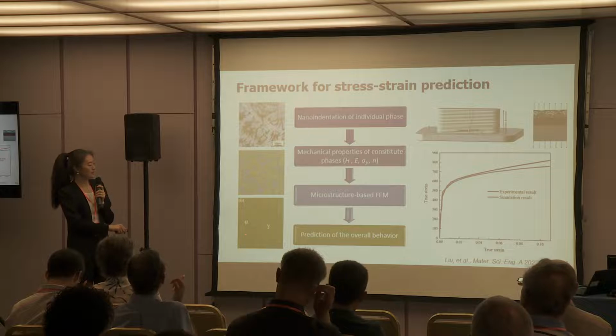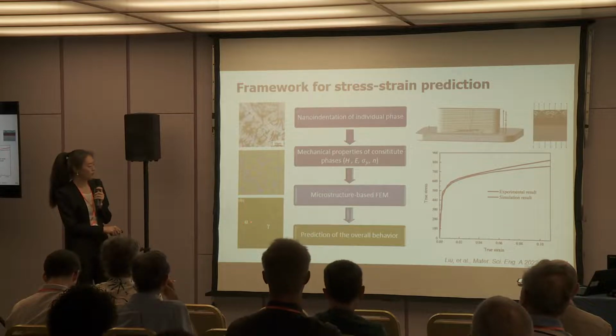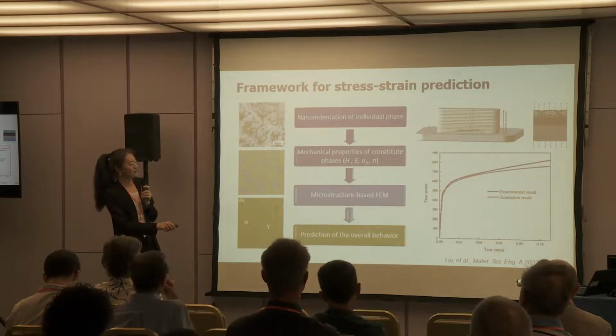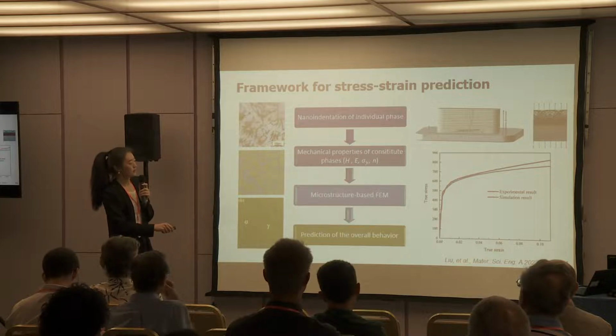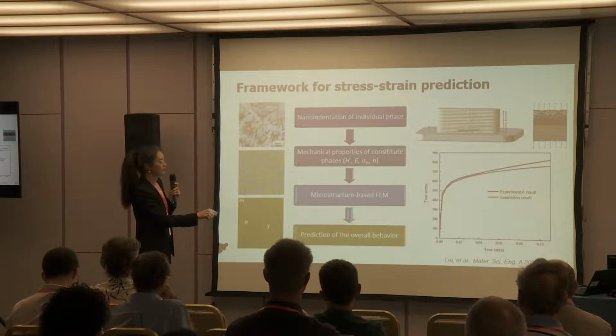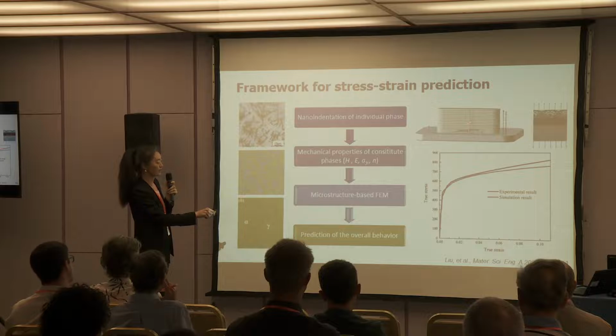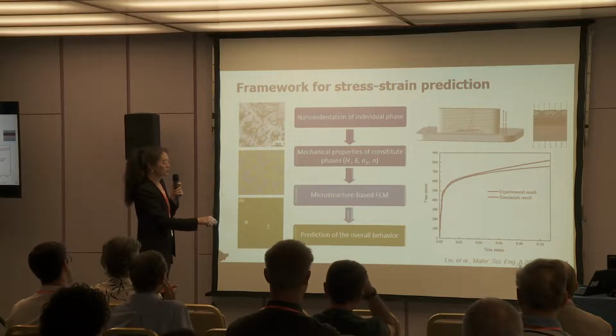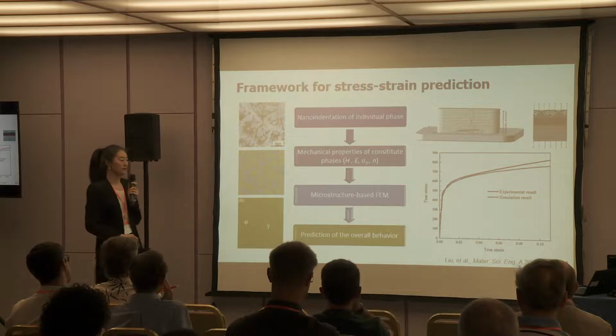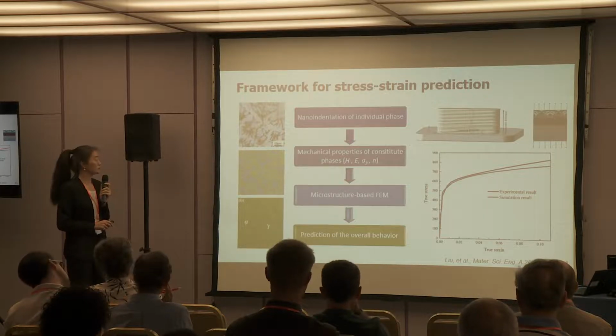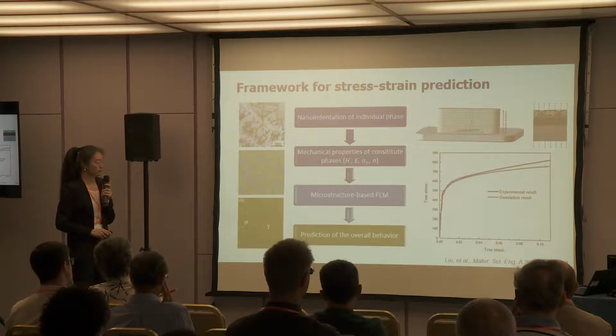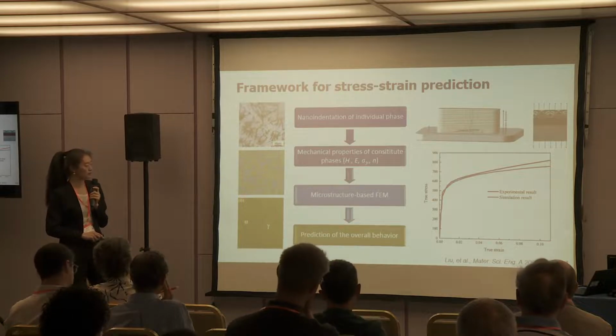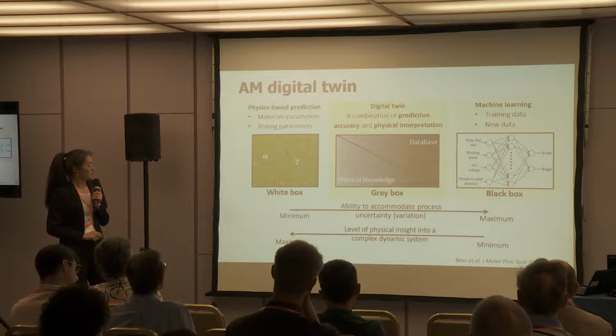Here I use duplex stainless steel as the example. And we can see that the predicted results agree very well with the experimental test. Experimentally, we investigated the middle 4 layers of this printed material by nanoindentation, and then cut the dog-bone structure to obtain the overall stress-strain behavior. And you can see that this is also a very useful framework for the stress-strain prediction of AM materials.